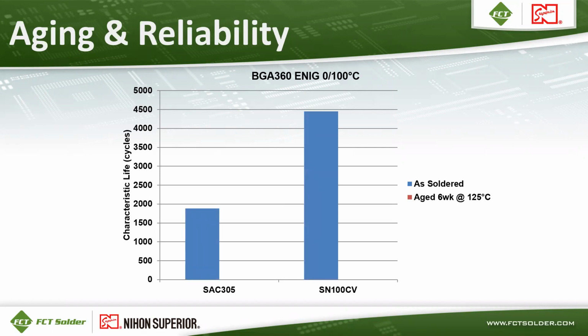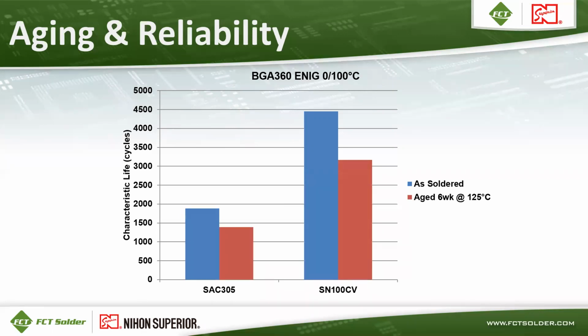Here's a BGA 360 on an ENIG surface. As soldered, SAC 305 has a shorter life than SN100CV. After aging 6 weeks at 125 C, SAC 305 still has a shorter life than SN100CV, although both lost some characteristic life from aging.